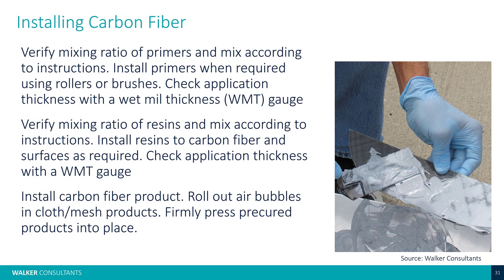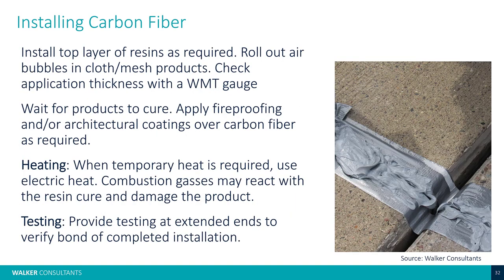And then install your carbon fiber product. Whether it's a sheet product or a fabric product, or whether it's a bar or a plate or something like that, you want to install that. You want to roll out any air bubbles, so you want full contact. You want full impregnation with the resins, and get this thing fully engaged. And then firmly press on it and make sure it's installed fully to the substrate. And then you want to install your top layer of resins as required.